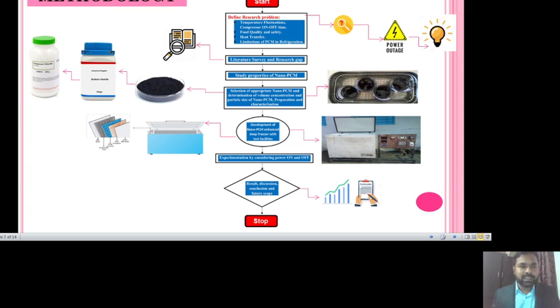We selected a very small mass fraction of NaCl and KCl, like 3 to 5%, because if we increase the percentage, it affects the suitability of materials like copper, stainless steel and MS. Similarly, the diffusivity also decreases. We are using graphene oxide nanoparticle because it has good thermal conductivity, good latent heat, good specific heat, as well as good density and good diffusivity, and we are keeping its mass fraction at 0.5. Why not more? Because if we increase the amount, then thermal stability reduces, lubricity also decreases and viscosity increases.